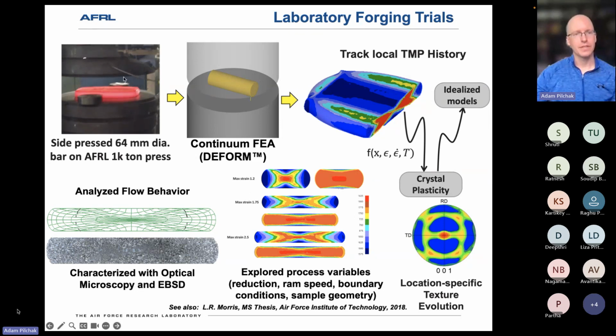We have a lot of experience with this and have well calibrated heat transfer coefficients and die friction coefficients, so we were able to quickly develop a continuum scale finite element model in the DEFORM package. From there we performed the simulations, looking at local strain rate, temperature history, some of the flow nets, and how the grains evolve during deformation. We did this for a variety of reductions, going from, I think, 60% all the way up to about 90% reduction.